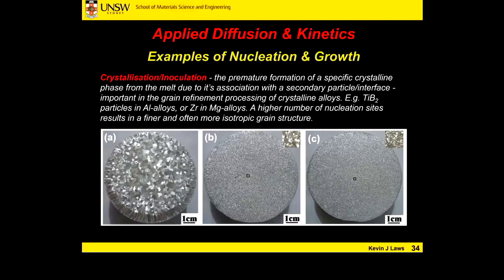And as we increase the volume fraction of titanium diboride, this grain size gets smaller again. We're essentially providing multiple tiny nucleation sites for multiple grains to grow very, very quickly. So that's why they're not growing big. They're being impinged on by other little grains that are growing at the same time, being inoculated from those titanium diboride particles.